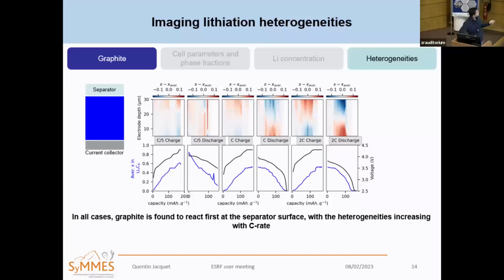As you're charging graphite, you're putting lithium in, and you can see that you find more lithium at the separator surface of your electrode. When you discharge, you're removing lithium, and you can see that this concentration gradient flips. As you charge and discharge at different C rates, you can still see the flipping of the concentration gradient, and you can also see that the concentration gradient becomes more and more intense.